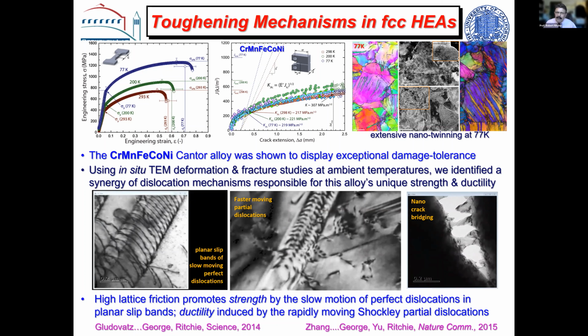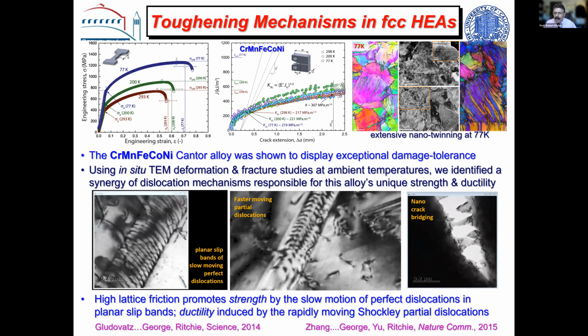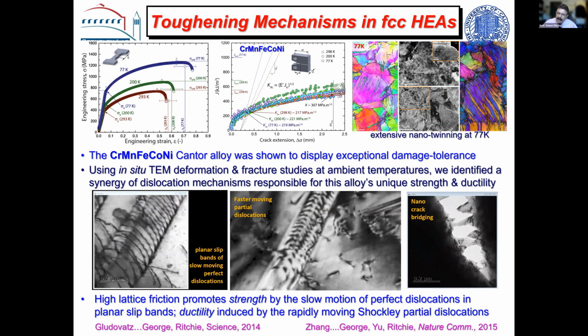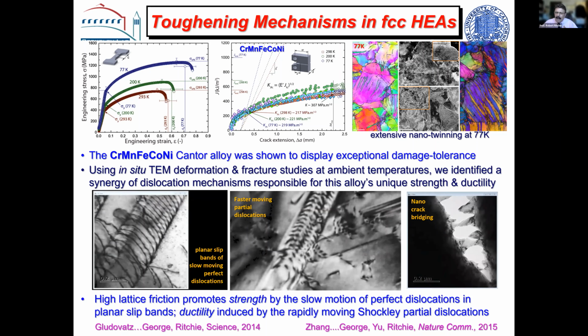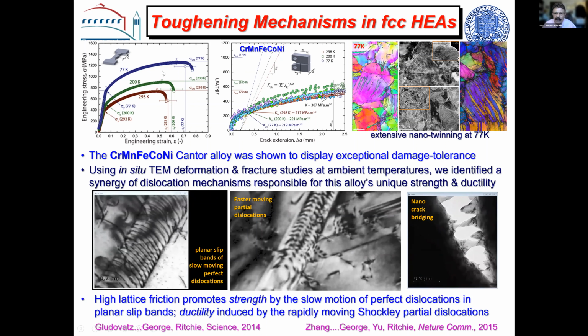And the result of this is you get strain hardening, because you get a different mechanism, initially dislocation glide and then stacking fault formation with partials coming in to give you further deformation. And this is what leads to continuous strain hardening. And when we get to lower temperatures, we get twinning, which is a third mechanism.